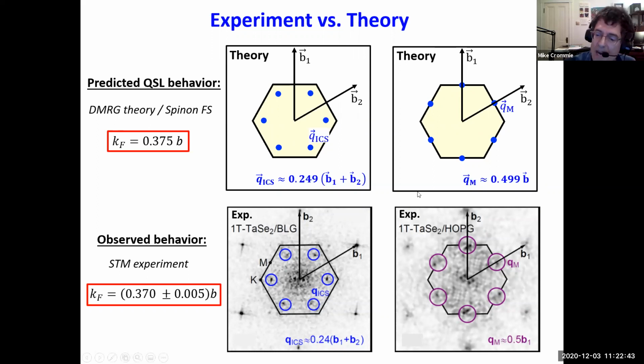There's a really strong match, and we can work backwards from our data to extract the Fermi wave vector of the spinon Fermi surface. What we get is 0.37 times B, which is the reciprocal lattice vector of the CDW, and we can compare that to the theoretical value of the spinon Fermi surface, which is 0.375 B. So it's a pretty good match. And so we see that the spinon treatment explains our data very well. We consider this to be very strong evidence for quantum spin liquid behavior in single layer 1T-TaSe2.